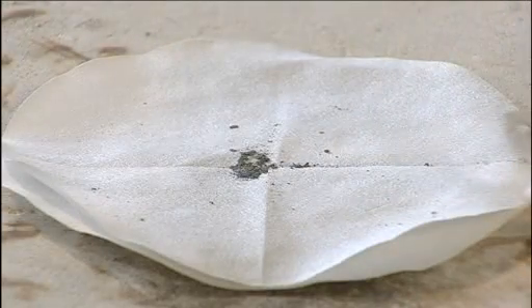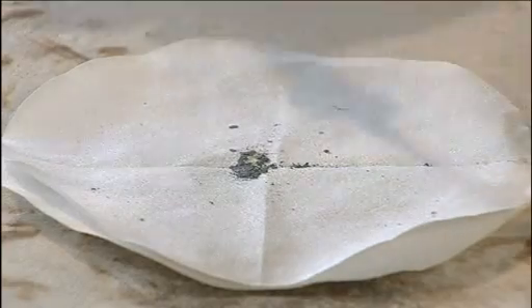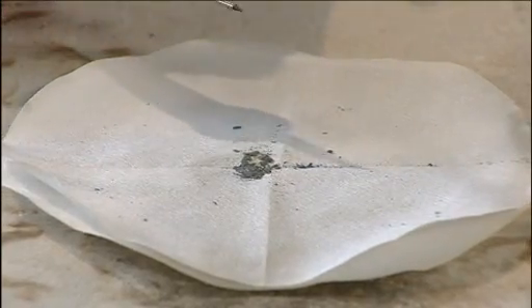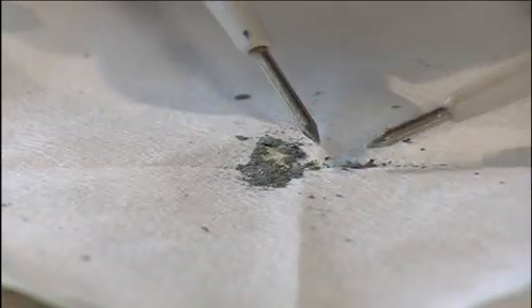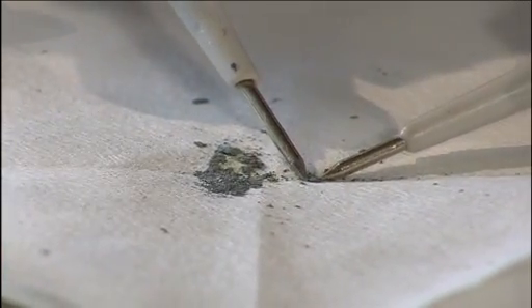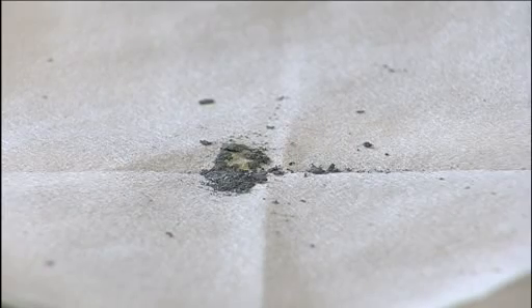You can filter the contents of the beaker to reveal the metallic zinc on your filter paper. This will need to be dried and then can be tested using a circuit tester. Since the chlorine was seen at the positive electrode, it seems likely that the zinc was produced at the negative electrode.